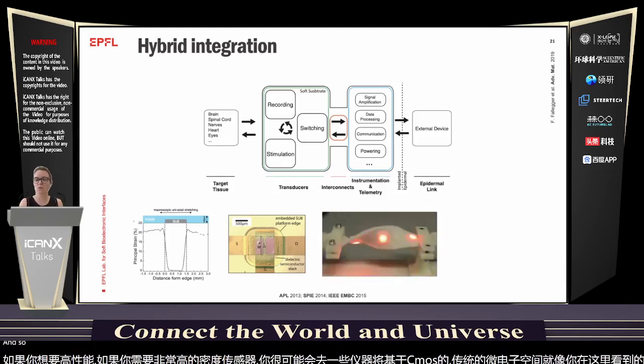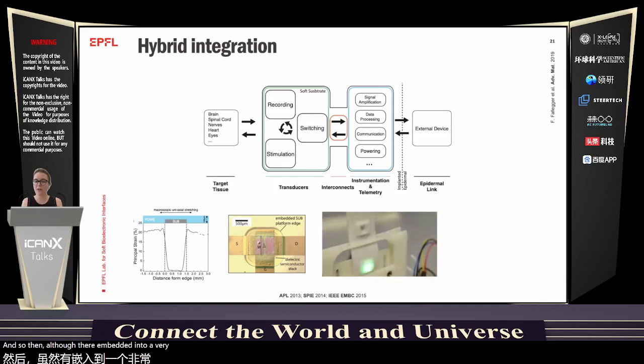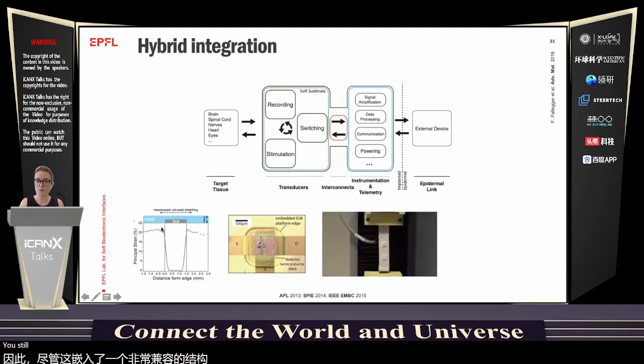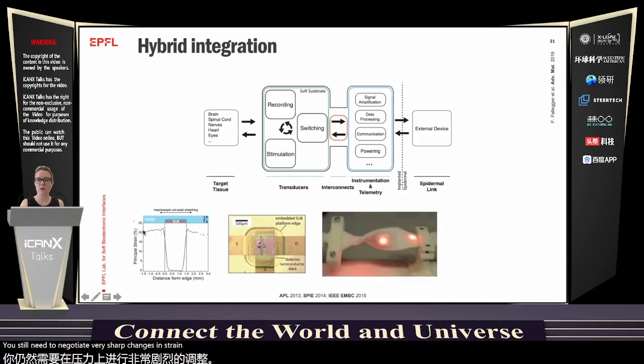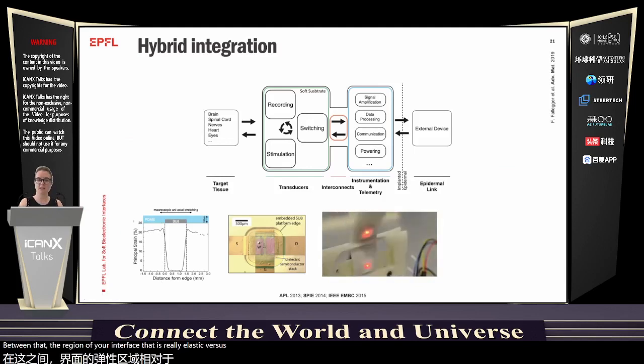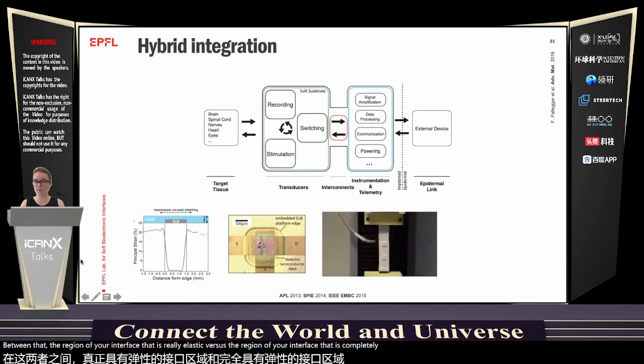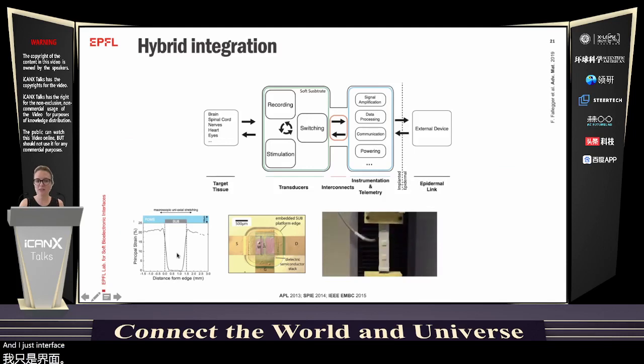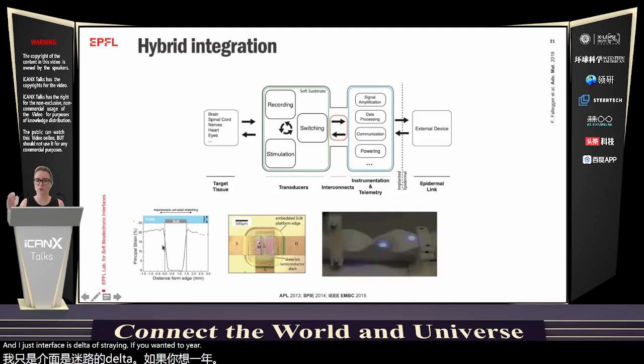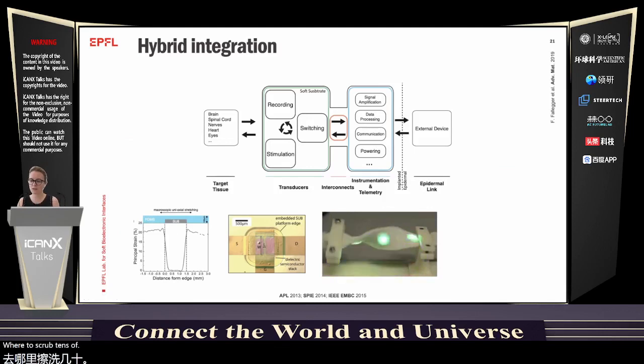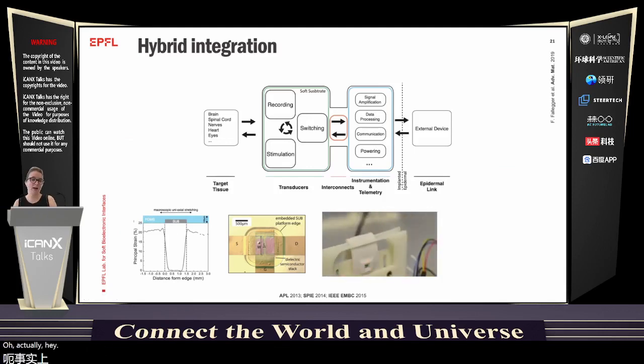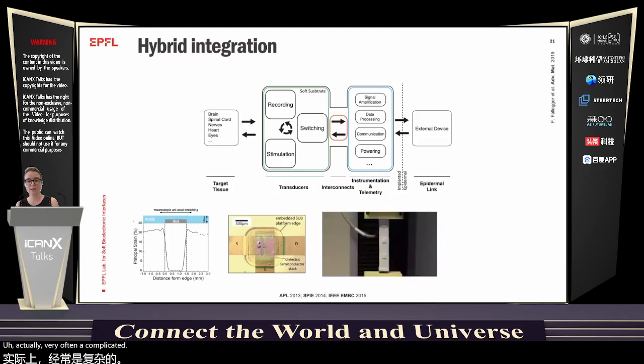And so although they're embedded into a very compliant structure, you still need to negotiate very sharp changes in strain between the region of your interface that is really elastic versus the region that is completely rigid. And at this interface, this delta of strain, which goes to several tens of percent, is very often completely catastrophic for the reliability and stability of the structure. In the center here, I put a photograph.